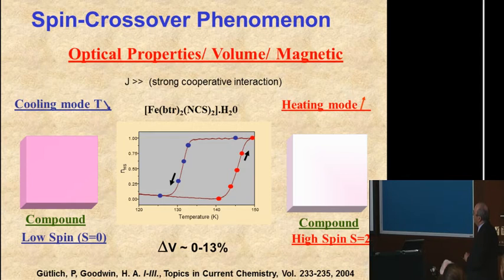This is the proportion of high spin molecules as a function of temperature. What you can see, if this interaction is quite strong, you can have a very nice hysteresis loop, a thermal hysteresis loop. That means that at a fixed temperature here, you can have two states, the state 0 and the state 1. And the characteristics of these states, you have two optical properties, so then you can read your information optically.